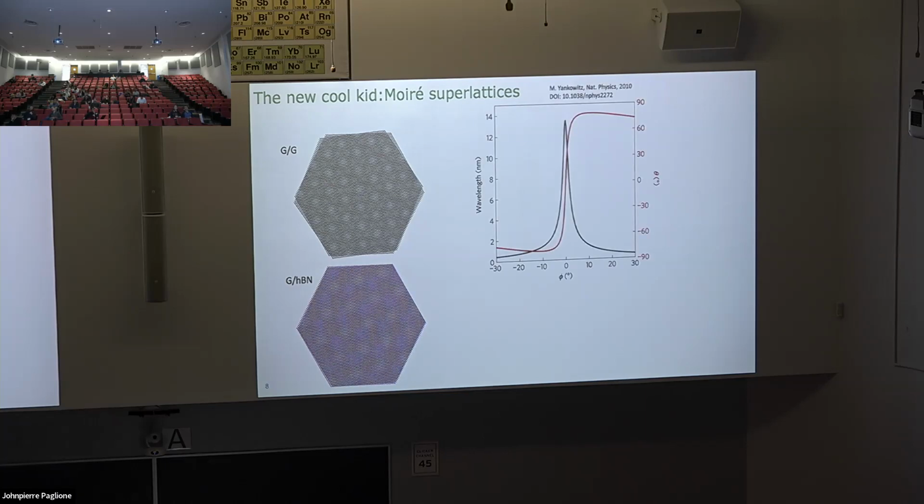That's it. It does that. So you can control the wavelength, the periodicity you're getting out of the superlattice, just by how much you control the twist angle. So here you have twist angle on the x-axis, and you have the resulting wavelength on the y-axis. And it turns out that this 10 nanometer regime is really where you want to be to see interesting physics in graphene and other 2D materials. And with conventional techniques, we were at the 40 nanometer regime, shaving off 1 nanometer at a time to get there. So this was a game changer.